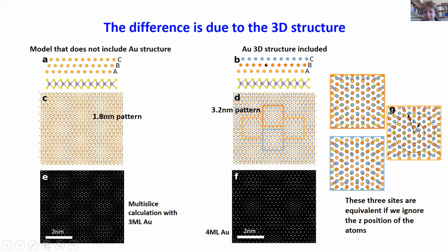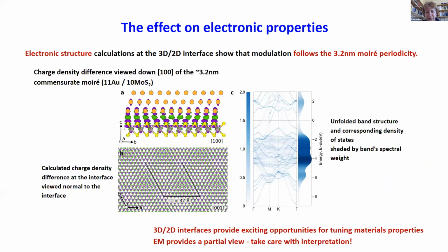But if you care about the height of the gold, and you only think about the correlation between the bottommost layer and the 2D material, you find that indeed the repeat distance is larger because these sites on the moiré pattern are no longer equivalent. So it's hard to explain in a slide something that took us weeks and weeks to think about, but there you go. There is a reason for it, and TEM is giving us only a projection view of what's going on. And this difference is important electronically because the electronic modulation is really most sensitive to the lowest level of atoms and therefore follows the longer period, the 3.2 nanometer period.